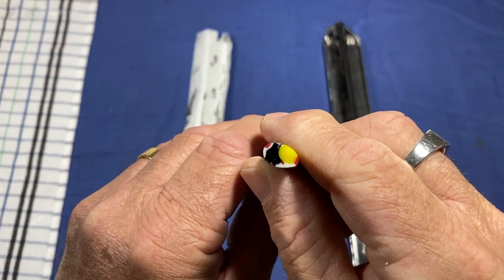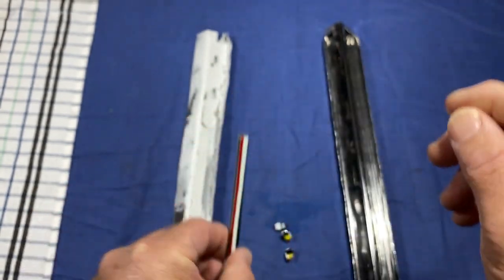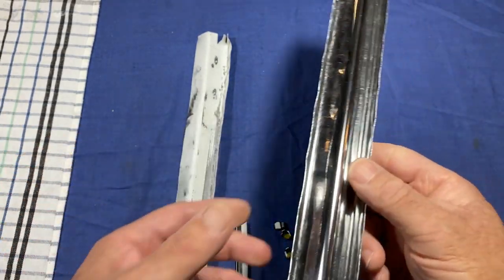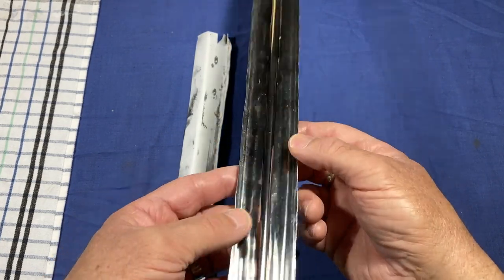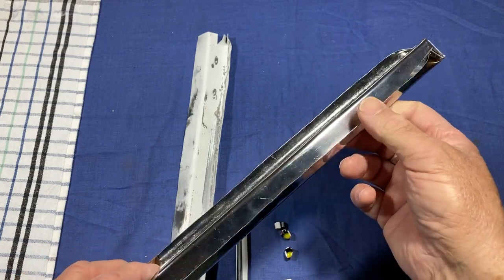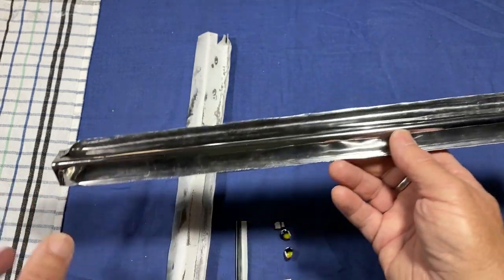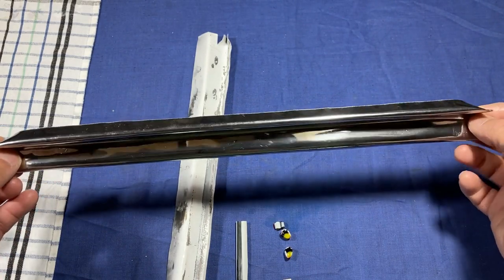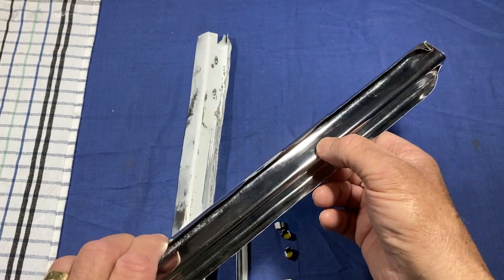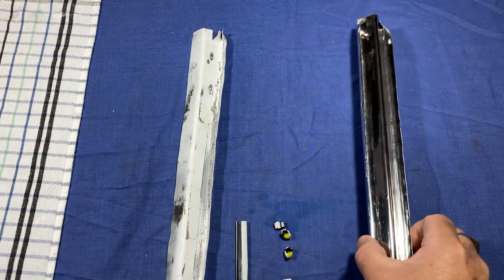I believe I used a rod, a couple of stringers, and some frit to get that pattern. Today I've made another mold from the same material, but this one is a double mold because I want to make enough murrini for a project. I shaped it around a piece of wood, hammered and knocked it around to get it into shape, and pinched the ends. First I'll put it in the kiln and take it up to about 700 degrees to burn off any manufacturing oils, then I'll coat it with boron nitride and make some murrini.